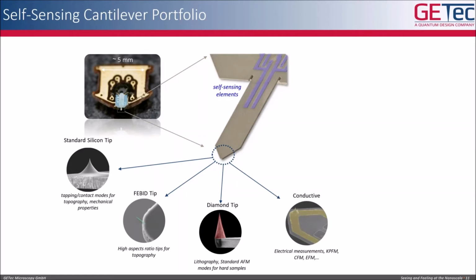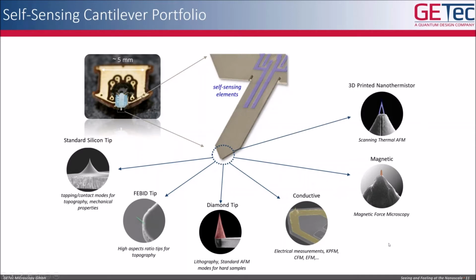And then we can offer more functionalities like a conductive tip for electrical measurements like KPFM, CFM, or EFM. We have magnetic tips for magnetic force microscopy, and as first prototypes, we are also working on thermal tips, which enable you to really do a thermal mapping of your sample inside the high vacuum environment of your SEM.